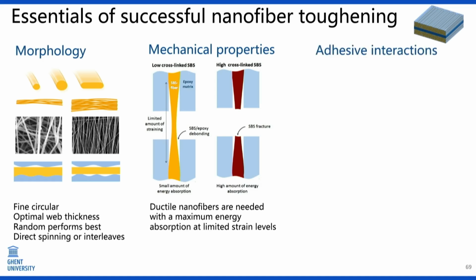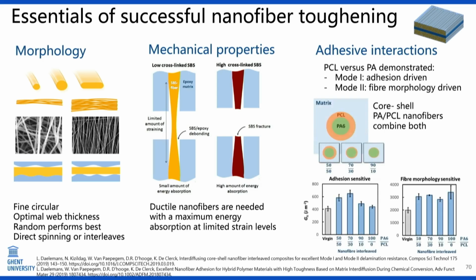Also, the adhesive interaction is important, especially in mode 1. Because if you do not have sufficient adhesion, you will just pull out the nanofibers, and then they're not active anymore either. For instance, PCL nanofibers give a very good adhesive interaction, but they dissolve in some of the epoxy resins. And then you lose the fibrous structure, and then they underperform in mode 2. Whereas polyamides perform very well in mode 2, but they don't have a good adhesive interaction, and they underperform in mode 1. And by using core-shell, of course, we can take the best of both worlds, and we could optimize both mode 1 and mode 2.